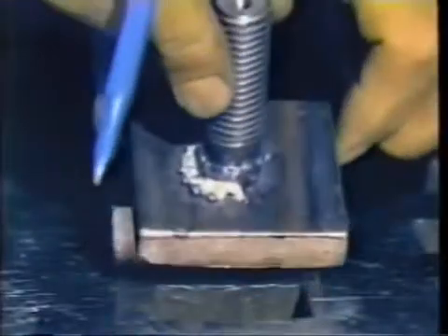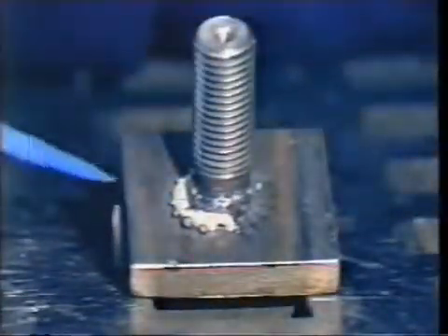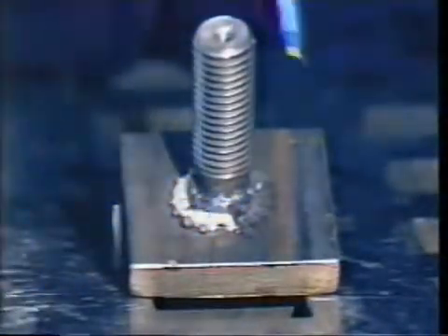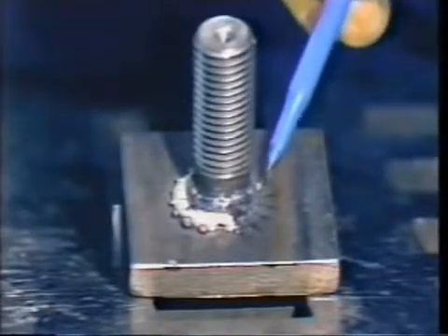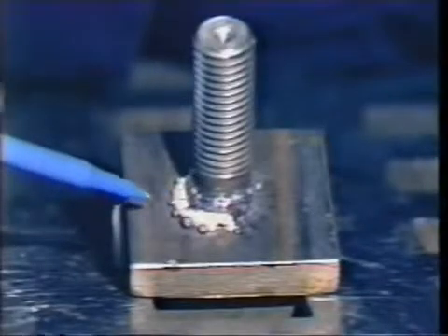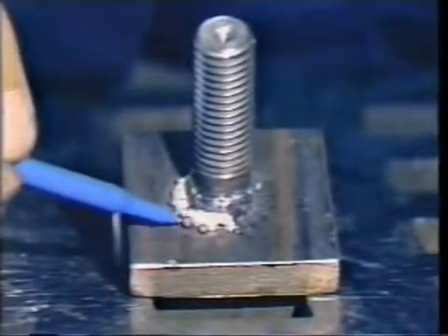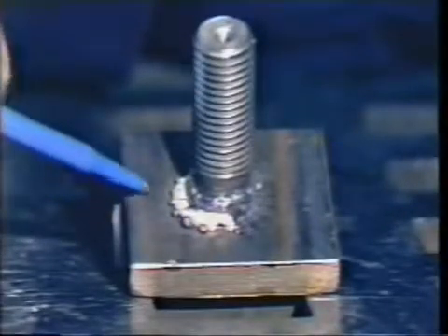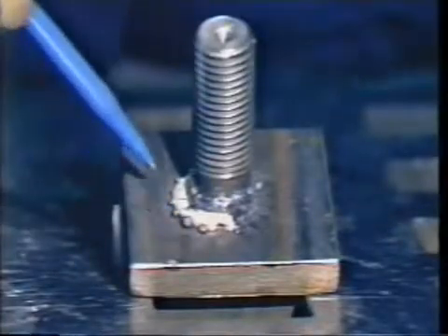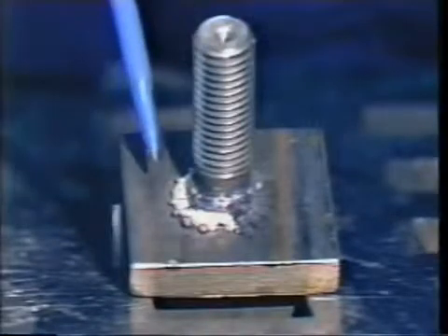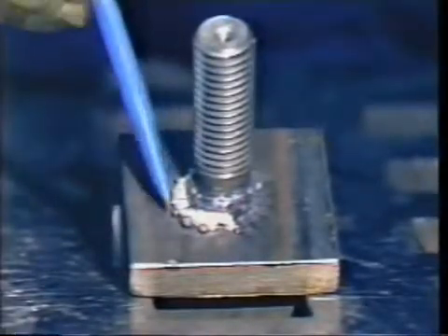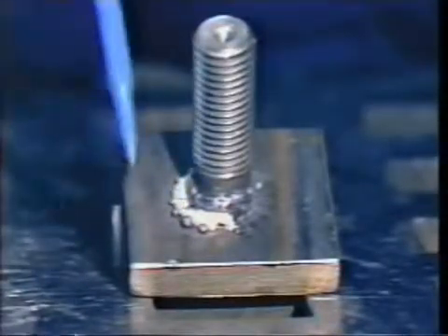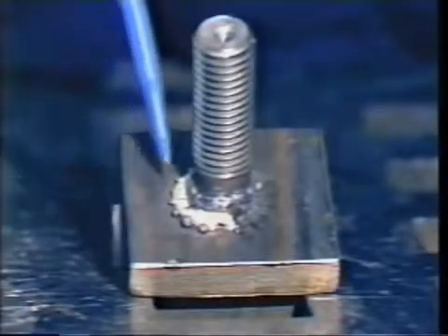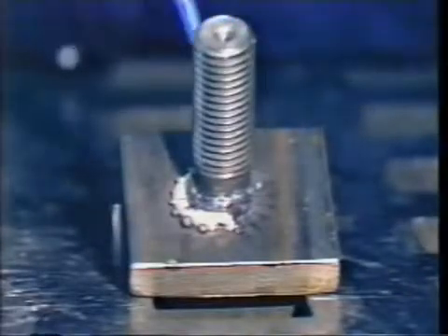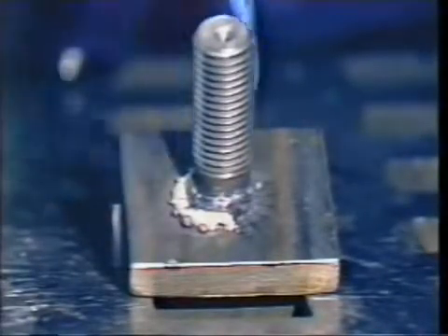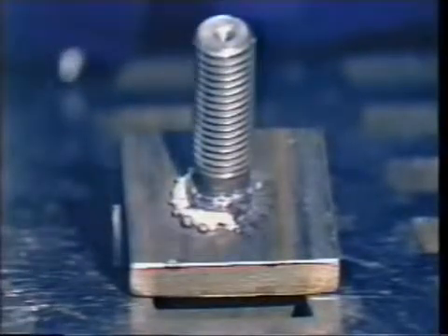An extremely cold weld is typified by a dull rather than a shiny fillet. You have a dull gray porous fillet. The other indicator is that the fillet material comes out the vents, but it adheres to the vents. You end up with stringers or spider legs coming from the vents. The material was just barely molten and slag-like, sluggish, rather than a weld berry coming out and being expelled away from the fillet. It is just barely fluid enough to be squeezed out the vents, and rather than rolling away and separating easily from the weld, it adheres and traps the ferrule material between the spider legs.